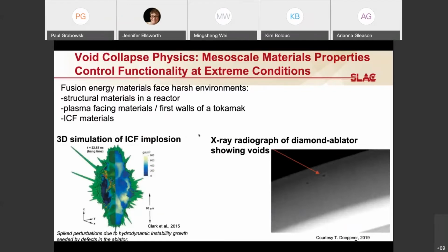So inertial confinement fusion, and in general, considering fusion materials, the environments in which they operate are harsh, and often the heterogeneities in those materials dictate the response, especially at extreme conditions. Shown on the left here is a simulation of an implosion for ICF, and the understanding is that notionally, if all things are going well, this should be a perfect spherical implosion, but we see these features that jet out, these spikes, and this is a consequence of seeding and propagating forward hydrodynamic instabilities.